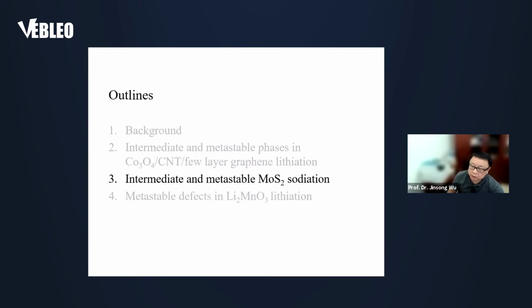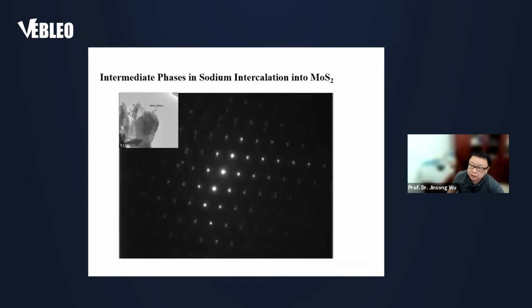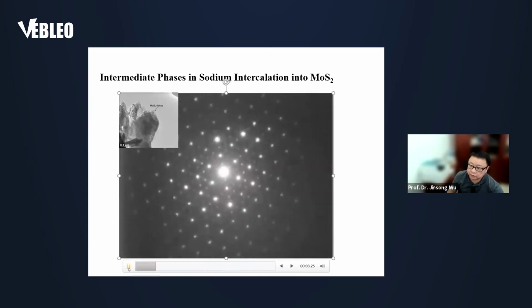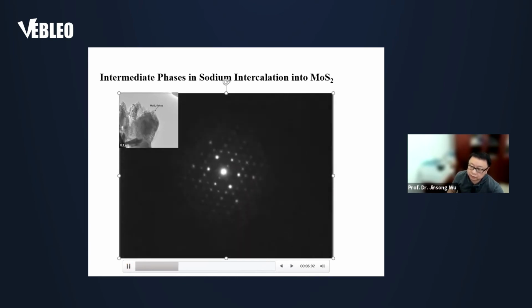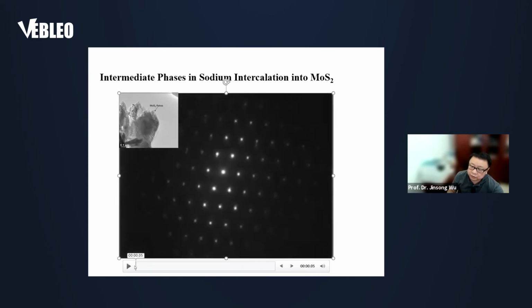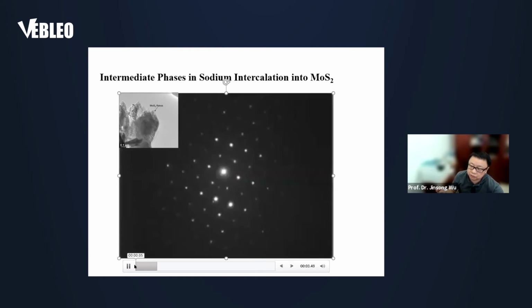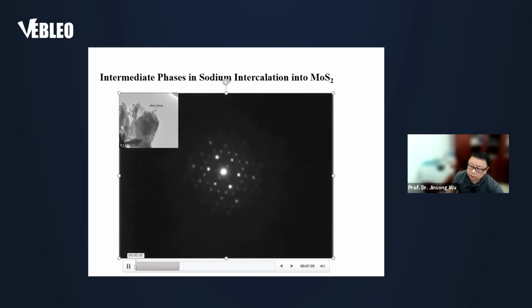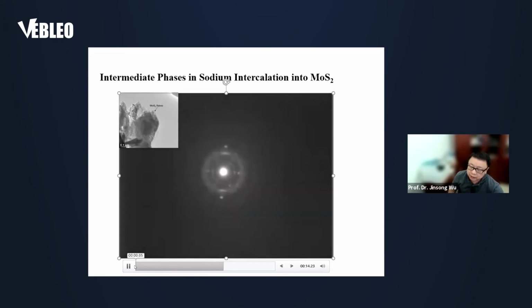The second one I want to show you is the intermediate and metastable structures that we found during the MoS2, the molybdenum disulfide, sodiation. And this time, instead of imaging, we use electron diffraction. We use so-called in-situ electron diffraction to investigate the sodiation process. Here's the sample, and what we did is record the electron diffraction. The advantage of using selected area electron diffraction is that we can truly reduce the dose. And once the electron dose is reduced, the artifacts due to electron irradiation damage can be minimized.